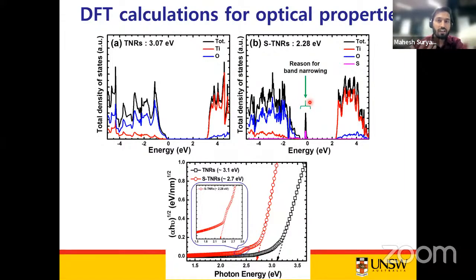What I would like to say here is that this double band gap behavior because of the sulfur doping is attributed to the gradient distribution of the sulfur doping concentration in our TiO2 lattice, and that is the reason why we have seen two band gap tails in the sulfur-doped TiO2 nanorod arrays.